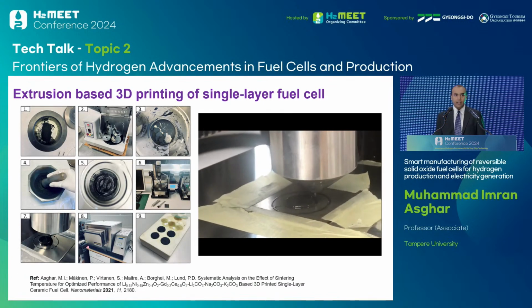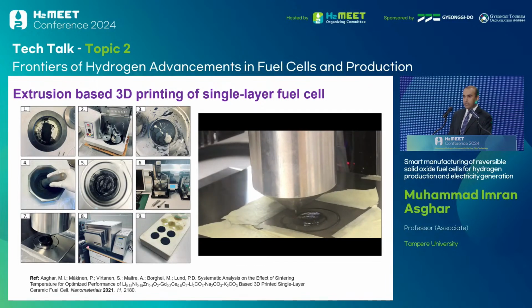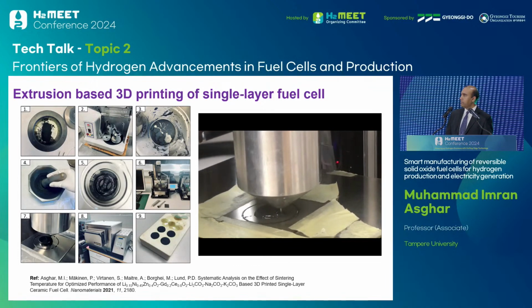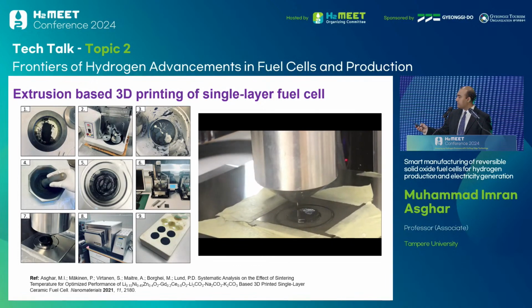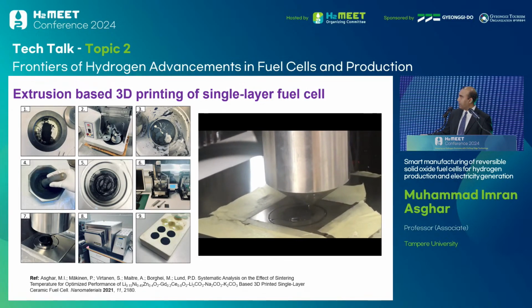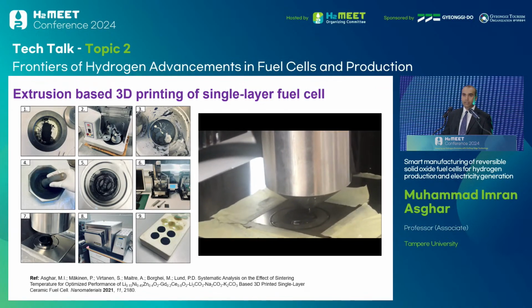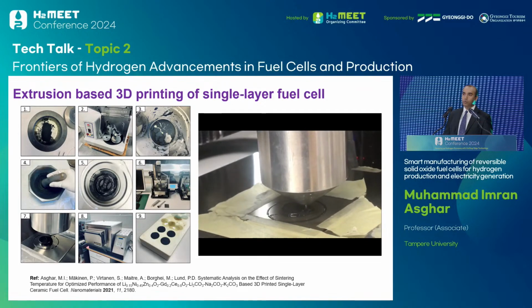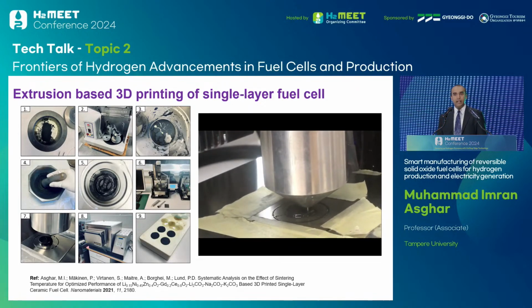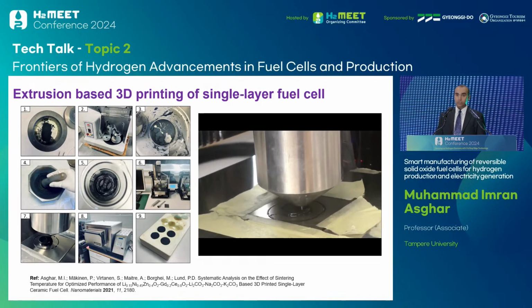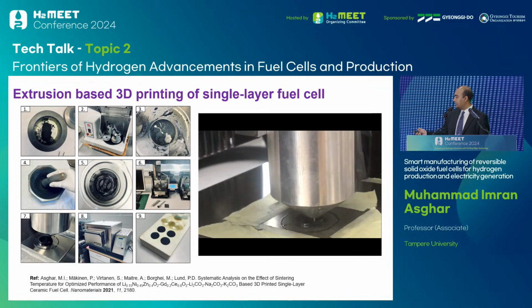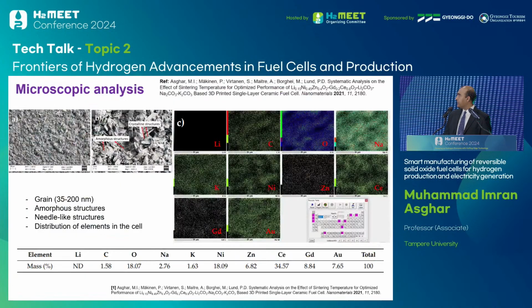So here you see additive manufacturing of our single-layer cells with extrusion printing. There we prepare our inks, and we do the printing after optimizing their rheological properties. Then we do the post-processing that involves debinding steps and also the sintering step, and then the cells are ready.